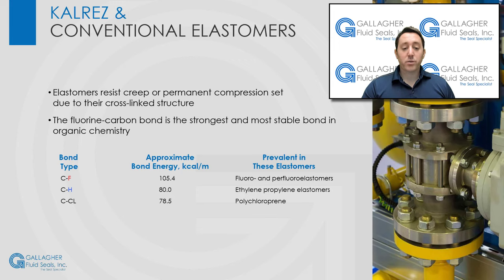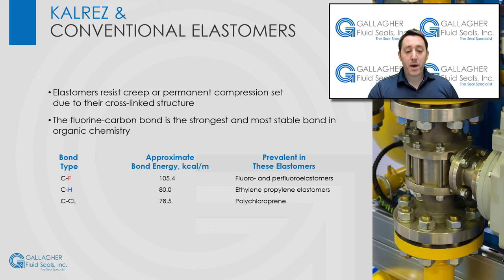Their compliant and flexible nature makes fitting and conforming to irregular surfaces easy. Plastics, like Teflon, tend to easily absorb particulate matter into their surfaces. Under dynamic movement, these surfaces can abrade or fret the surface of the metal mating part causing leakage. Elastomers, having lower contact areas as seals in most designs, also tend to shed particulate matter. Thus, they do not have the fretting problems of Teflon. This helps maximize the surface life of mechanical seals.